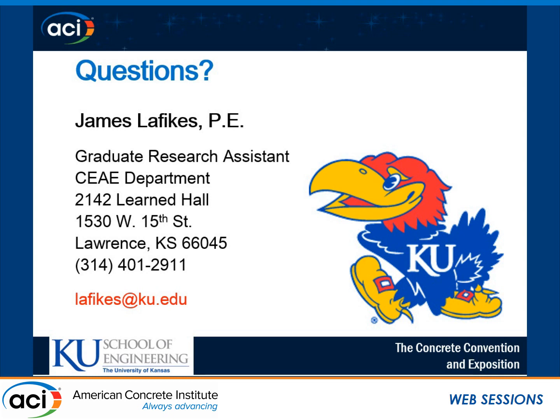Good. That's a good point. We tried to keep consistent as much as we could with KDOT, or Kansas DOT, low cracking, high performance concrete specifications, which is our air content range there. It's 8% plus or minus 1. Well, I like 8%. It's just that so many times we don't see them in many of the DOTs and in the private sector. Second thing is that, once again, I really like what you did. It's good stuff. In future work, you may want to take another look at SCMs and their effect. I typically tend to see more plastic settlement cracking with SCMs and with higher dosages, but that's out on actual bridge decks, other types of suspended slabs. Excellent, thank you very much. Thank you. Good points.